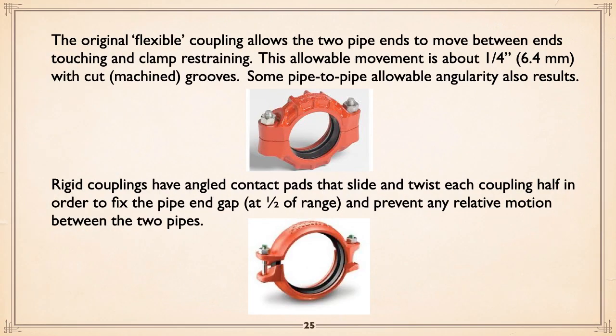Now, the original flexible coupling allows the two pipe ends to move a little bit and move in and out a bit. That in and out is from touching to about 1/4 of an inch using cut grooves. Because of that, you're also allowed some angularity.